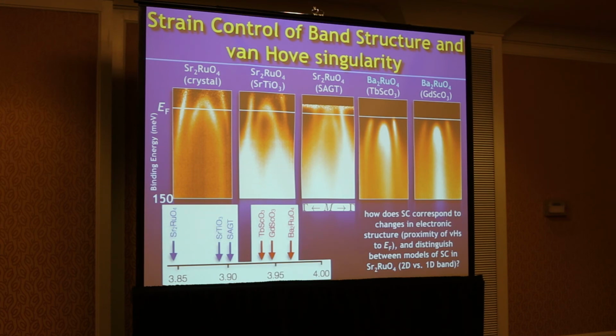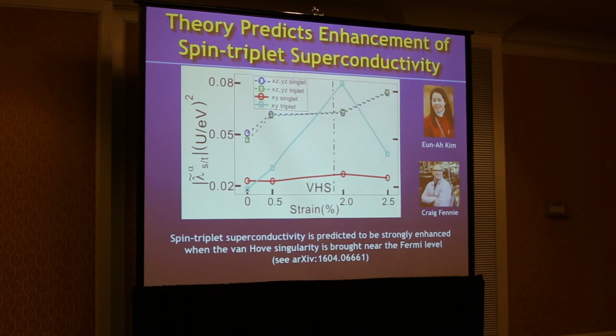and change the band structure of the material, our theorist colleagues see that there's something very interesting in terms of Tc. This vertical axis here, I'm told, is somehow related to Tc, in units that only a theorist can love. But as we're going along the strain axis, indeed the transition temperature should go up drastically as we get close to this Lifshitz transition. Well, this is an opportunity. We need to have cleaner films. Okay, maybe I haven't pointed that out. Our films are not superconducting yet. But the opportunity to combine this approach between using single crystal substrates and films, I think, is enormous to access hidden ground states that have better properties and provide theorists with meaningful feedback.